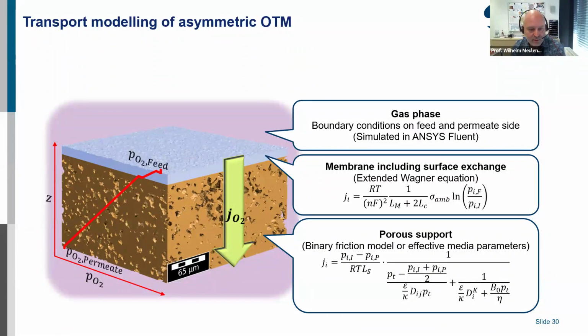And then most people said, let's reduce the thickness of the membrane, because already Henny Bouwmeester showed that in principle, if you reduce the thickness, we can increase the performance, but that is also not completely correct. And we had a recent PhD work, which is ready and is currently in the printing phase. Here we demonstrate that not always the material or the thin film is determining the flux, because if you have, for example, BSCF, the flux of the material and the surface reactions are so fast that the support is the limiting step.